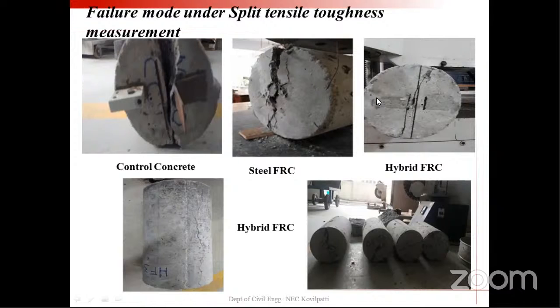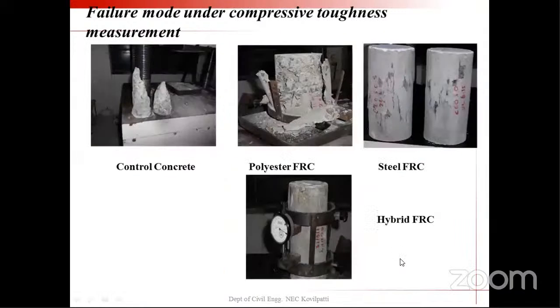And in the last picture, you can see the hybrid FRC. You cannot even see where the failure has occurred. Only one single crack has passed. So this is a crack which has occurred in the hybrid FRC specimens. So these are the specimens tested. Even though they have undergone severe loading, we cannot see a big cracked matrix in these pictures.